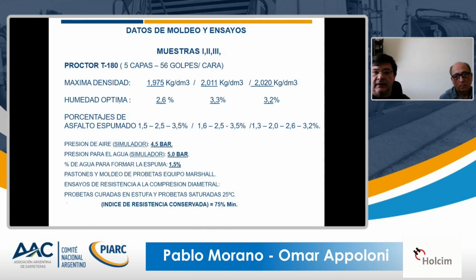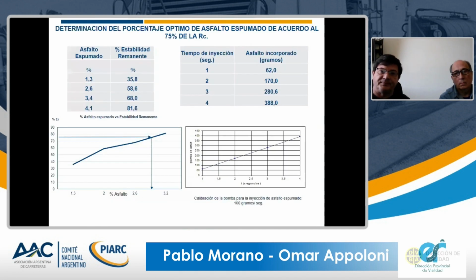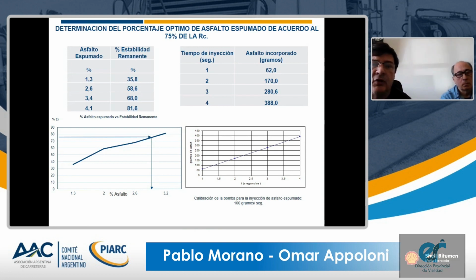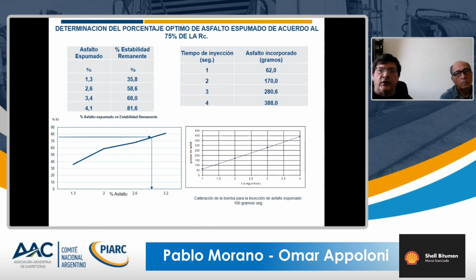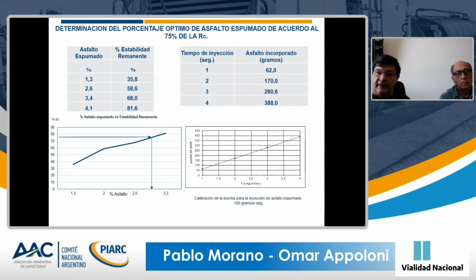the molding of the cores was using a Marshall equipment, and we did resistance testing and diameter compression with cured cores using a resilience index that was at least 75%. Of the 3 samples or cores that we used for the tests, the one that gave the best results was core number 3.